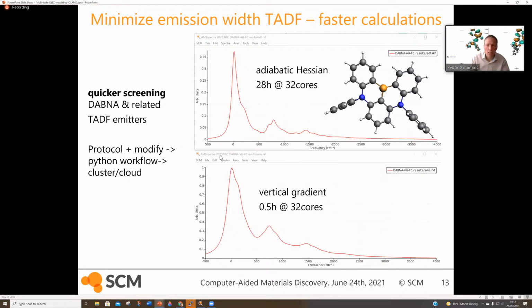And for these type of molecules, we're also building workflows to make the calculation much quicker. Since you need the excited state frequencies, they're typically quite expensive. So for a molecule like this, it would take around 28 hours on a 32 core machine. But by using different types of approximation, you can narrow it down to around half an hour. So you can do the calculation roughly 50 times as fast.